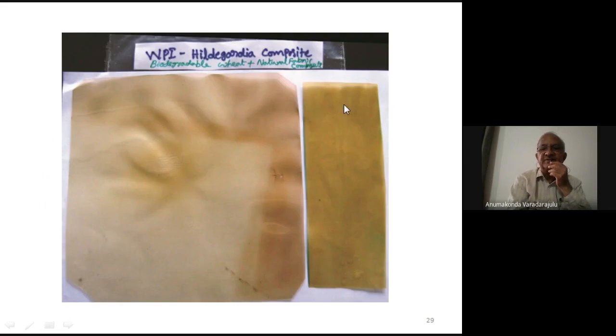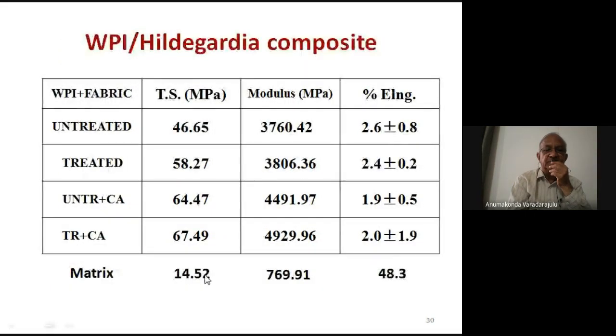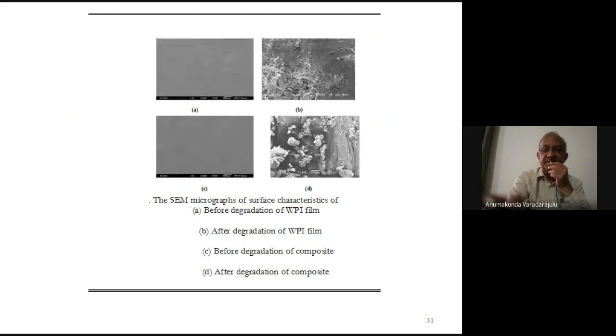So this is a matrix film, whereas this is the composite film with the same fabric, and the matrix was having so many wrinkles, but the composite is a uniform one. The matrix was having a tensile strength of 14.5 megapascals, 769 modulus and 48.3% of elongation. But when we treated the fiber and then used the coupling agent, the strength has gone to 67.49 megapascals, the modulus has increased to around 4,900, and the elongation came down from 48 to 2%, which is the required elongation for carry bag purposes.